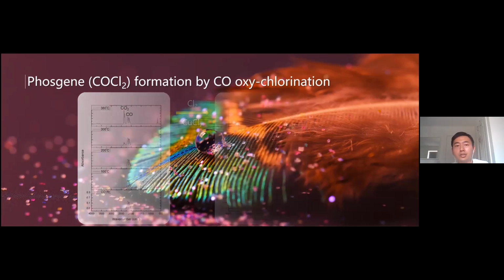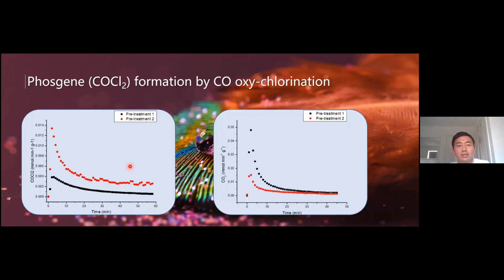But there's another issue: the more dichlorine we used to treat the catalyst, the more phosgene we could produce. Like the picture shown on the left, the red one had more treatments of dichlorine, and we had more phosgene formation. Meanwhile, the CO2 formation was reduced in these different treatments. But we could see that the reaction product decreased with time.